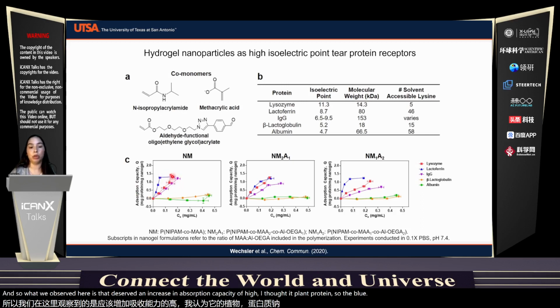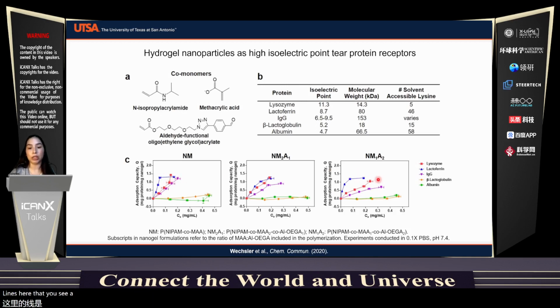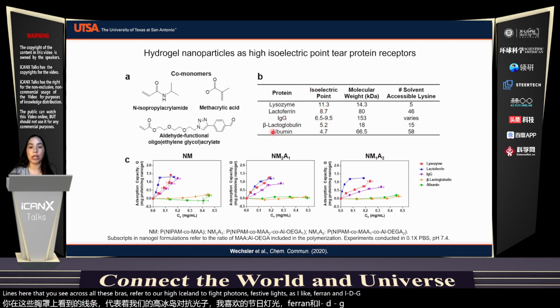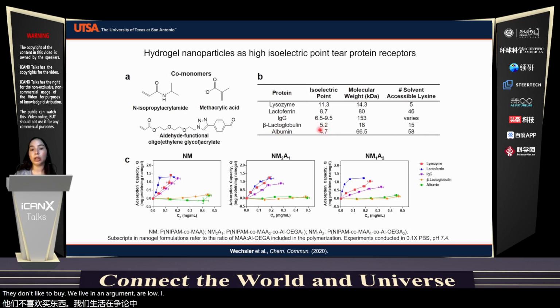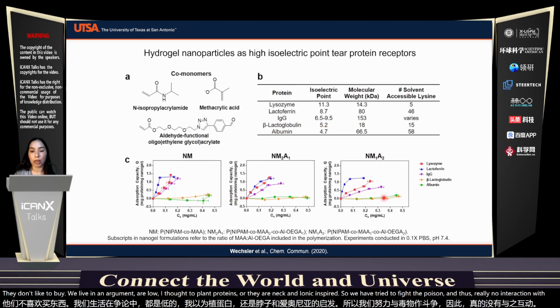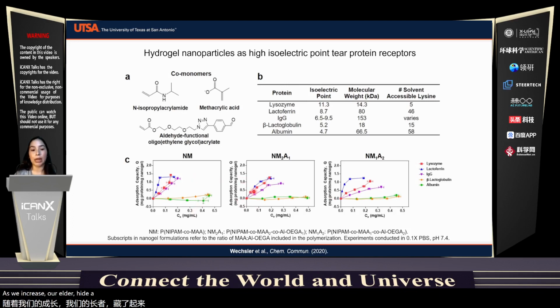So the blue, red, and purple lines here that you see across all these graphs refer to our high isoelectric point proteins tested, lysozyme, lactoferrin, and IgG. Beta-lactoglobulin and albumin are low isoelectric point proteins, or they are net anionic in charge. So we have charge repulsion, and thus really no interaction with any of our nanogels tested. As we increase our aldehyde component in our hydrogel, we start to see some separation in the adsorption capacity here. However, what we noticed in this experiment is that these interactions across all these nanogels tested are primarily driven by electrostatic interactions.